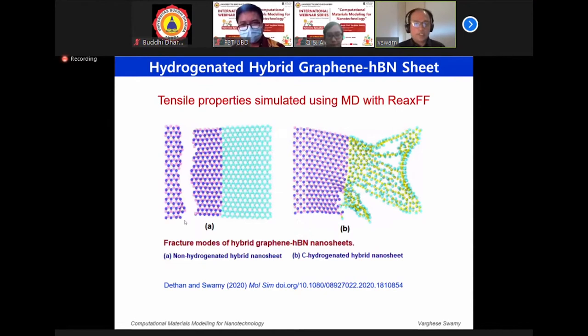Now, this figure here shows, to the left, fracture modes of two situations. In the first case, A here is the fracture mode of the non-hydrogenated hybrid sheet. When you pull it, it withstands stress up to about 178 GPa, and after that it cracks. But the crack appears in the boron nitride segment of the hybrid. The carbon segment is intact.